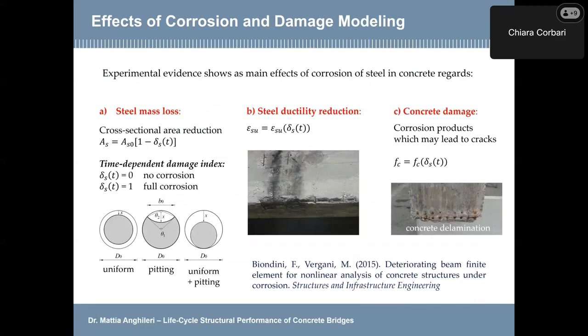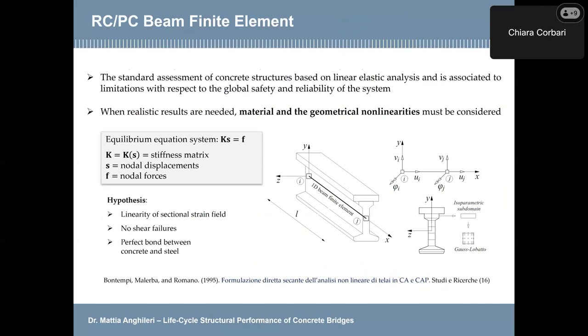Starting by considering the effect of steel corrosion, the experimental evidence clearly shows that the main effects of corrosion of steel in concrete regard three main topics: steel mass loss associated with cross-sectional area reduction, steel ductility influence, which may lead to a reduction of the ductility and therefore to brittle failures, and also concrete damage associated with the corrosion products that are generally introduced in concrete. These kinds of effects are generally modeled through time-variant damage indices calibrated based on experimental data.